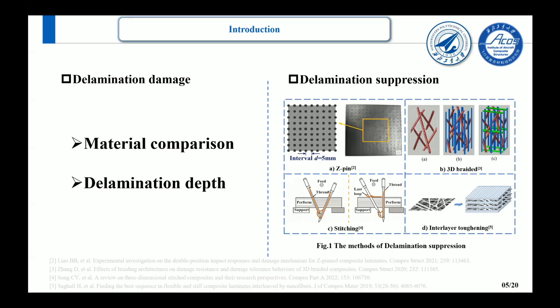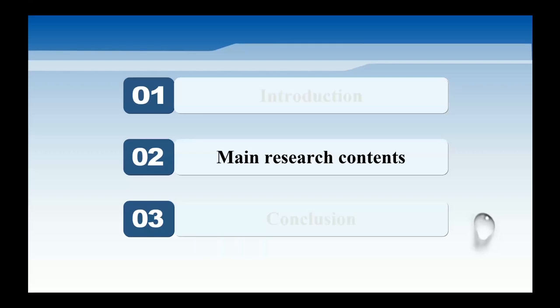The literature survey has identified that three key problems have not yet been adequately addressed. Firstly, how to select materials for aviation structures susceptible to delamination. Secondly, a more comprehensive analysis of the effect of delamination depth on residual compressive strength needs to be done. Furthermore, currently available methods such as Z-pin, three-dimensional braided, stitching, and interlayer toughening have been found to demonstrate fairly significant improvements in suppressing delamination damage under low-velocity impact energy. Moreover, these techniques can adversely affect the in-plane properties of the original structure. To address these challenges, we propose a research plan centered around three key aspects.